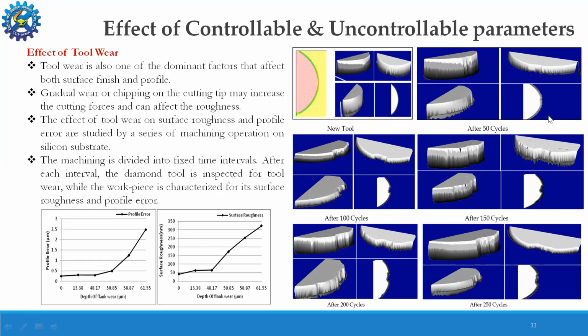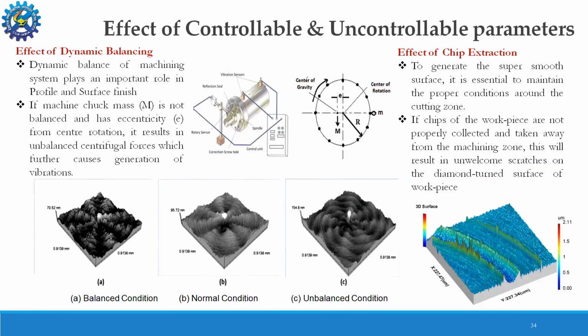So these are the images of the diamond tool. This is an image of a new diamond tool, which is an unused tool. Then after 50 cycles, 100 cycles, 150 cycles, 200 cycles, and 250 cycles, we could determine what the life of the tool is and at what time we should stop machining with that tool so that it does not affect the optical components which we are fabricating. So we arrived at very significant results which have been used for the fabrication of optics further.